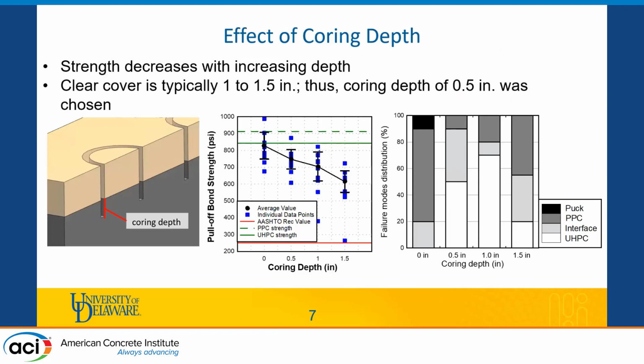So before continuing our tests on the surface prep methods, we needed to decide both the coring depth and the overlay age. Starting with the coring depth, what I mean by that is how deep we go into UHPC, as this illustration shows. So we tested different coring depths varying from 0 to 1.5 inches. And we noticed a decrease in bond strength from approximately 820 PSI for 0 inches to approximately 610 PSI for 1.5 inches. This decrease in strength is explainable by the increase in probability of having a weaker point in our material the longer our core is.